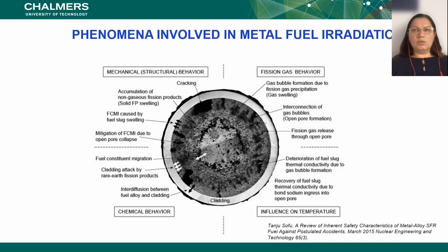And of course, we have the fission gases, which from one pin is not much, but if you think about the core, then you have quite a bit, and you have a lot of iodine released. And of course, iodine is known to be one of the first to affect a human being if it's released in enough concentration in the air. So of course, this is a very important part to be known and to be studied. So as you can see, this is a cut through a high burn-up fuel. This has been a metal alloy, so it's not an oxide alloy, by the way. So I think that we are going to the next page.